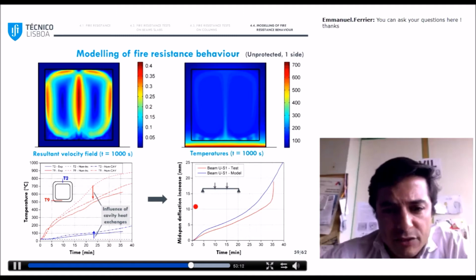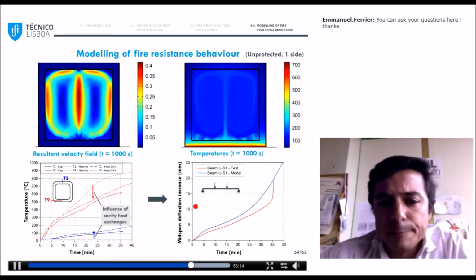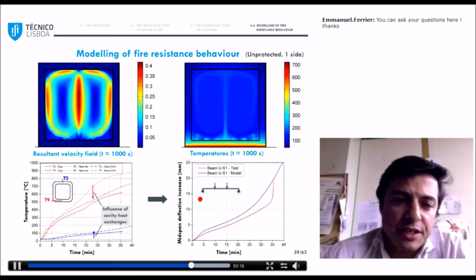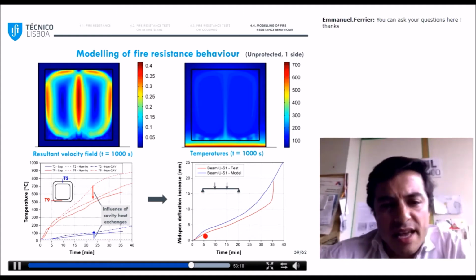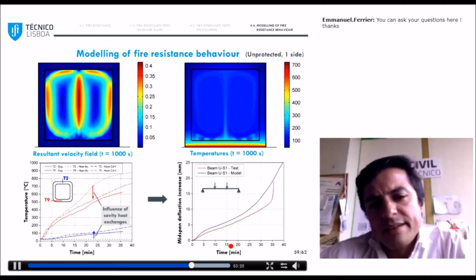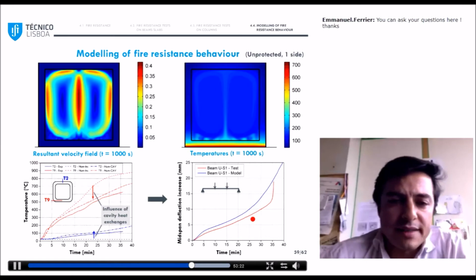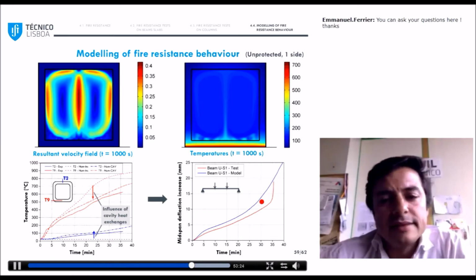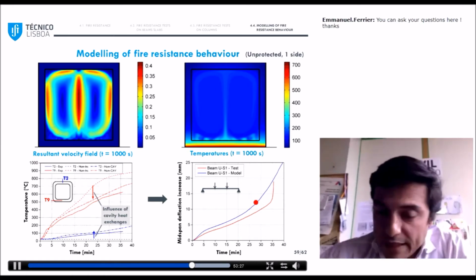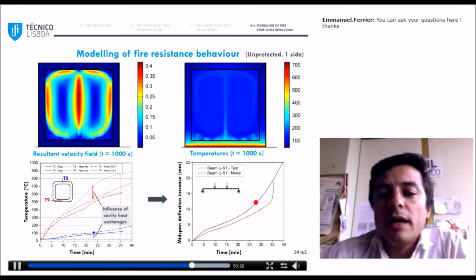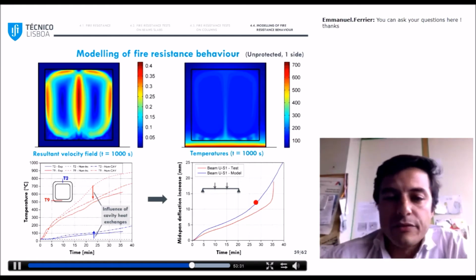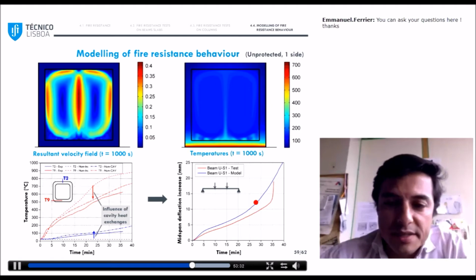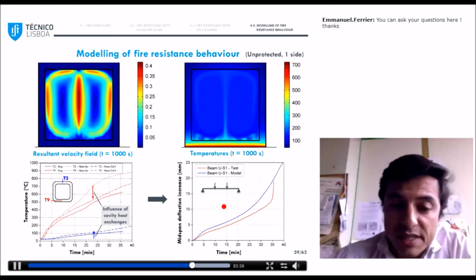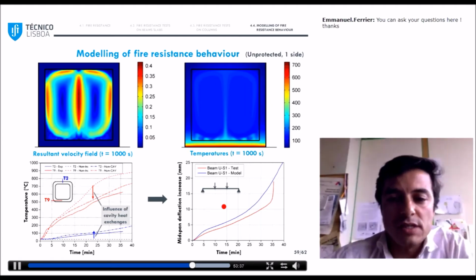At your right-hand side, you can see an example of the midspan deflection increase for one of the beams as a function of time. Again, the comparison between the test in red and the model in blue, so without failure criteria, I should note. But given the complexity of the phenomena involved and all the uncertainties at stake, I would say that the agreement is quite reasonable.